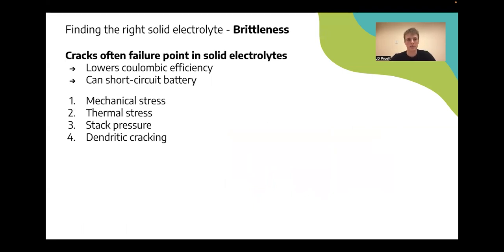The second really key point is that cracks in the solid state electrolyte are one of the most common failure points in these solid state batteries. Cracks seem pretty intuitive, but they lower coulombic efficiency. They can cause shorting in the battery. And so these batteries need to be able to undergo certain levels of mechanical stress, thermal stress. I'll talk about stack pressure in a few slides. And they need to be resistant to dendritic cracking. And this is what I'm going to focus on now.